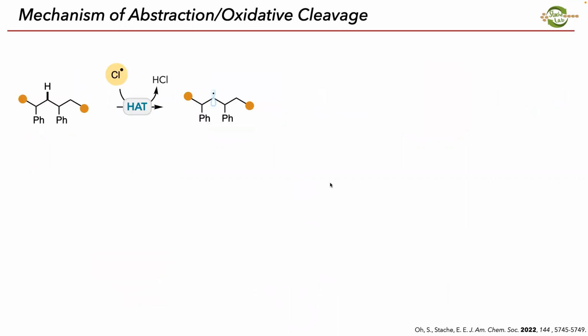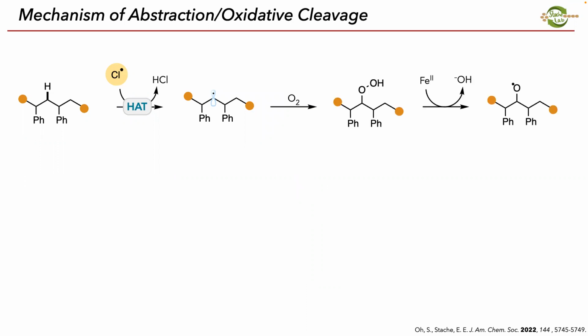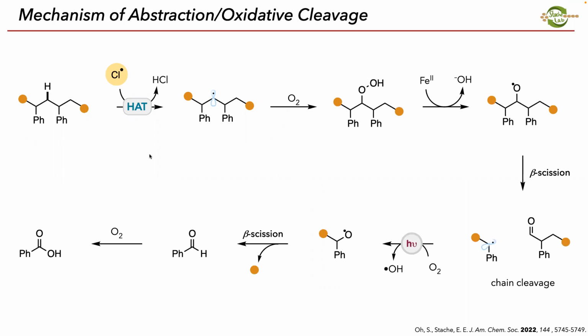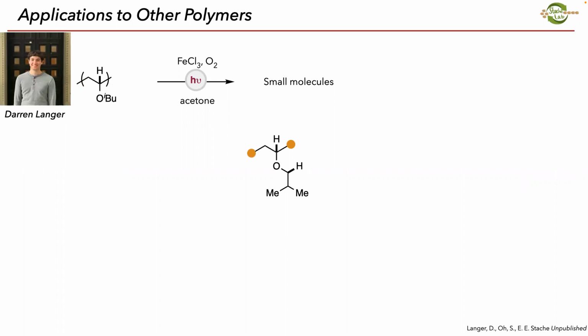The mechanism is shown here very briefly. I'm just going to go through this really quickly. It's a little bit technical, but basically we abstract hydrogen atoms, it reacts with oxygen, starts to cleave the backbone, generates benzaldehyde, and then that gets oxidized to benzoic acid. And there's a few different pathways I can go on here, but I'm just going to skip over those for now. We also propose that this is one of the CH bonds we abstracted, but the other one we can also abstract to get benzoic acid.